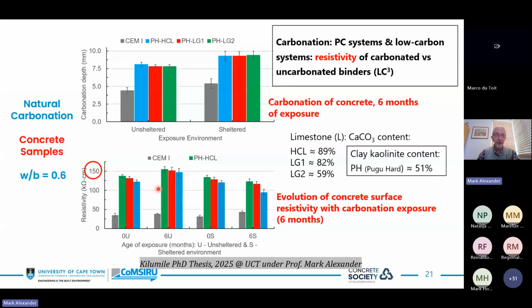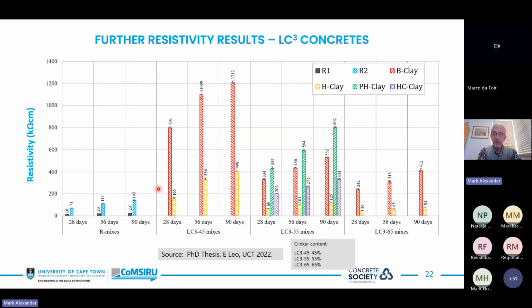So this is really interesting data, and it seems to contradict to a large extent some of the accelerated data that is coming out. This is also work that was done on kaolinitic clays from Tanzania. There's some superb clays up there. And you can see here, this is Portland cement and slag concretes. Way down here, less than 200 kiloohm centimeters. But even that, at 100, these materials are still superb. Well, a previous student of mine, Emmanuel Leo, was measuring these kinds of values. Actually, I asked him, do you really believe those values? And I don't know if I do believe them. They were measured in our own lab with our own equipment, and I'm still not sure that I believe them.